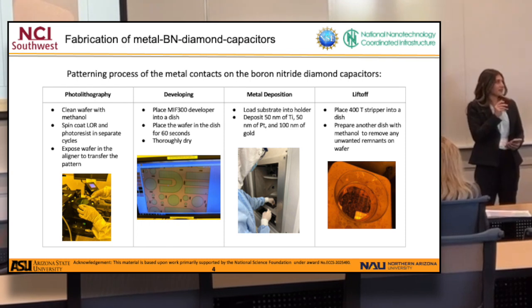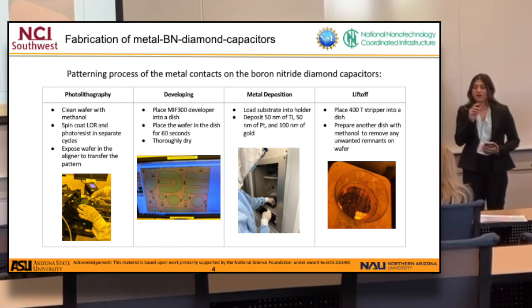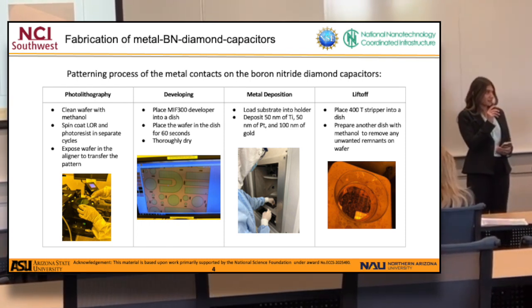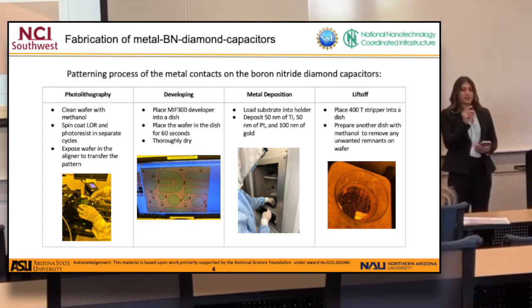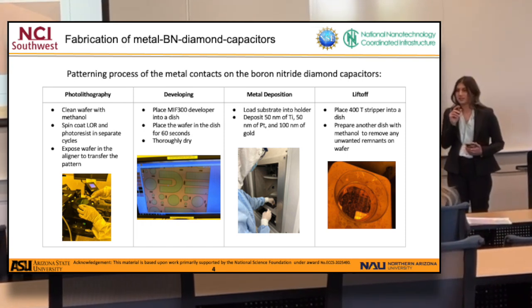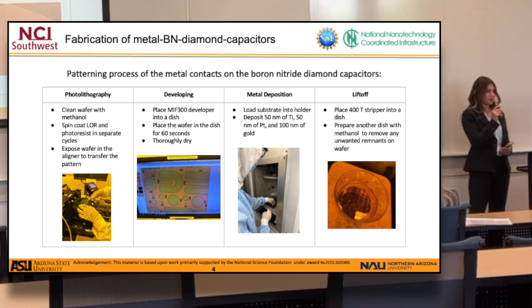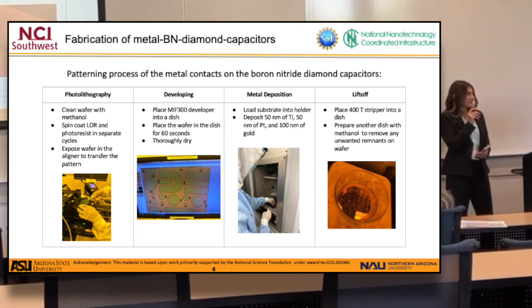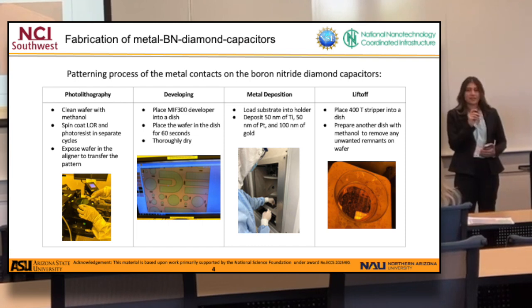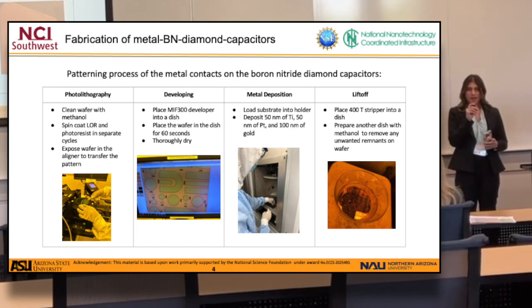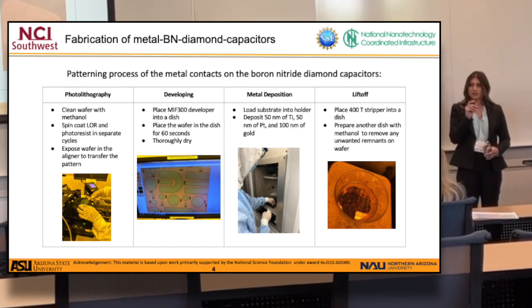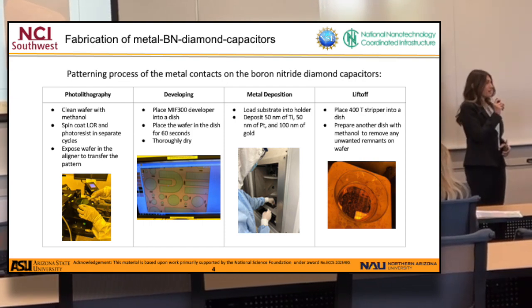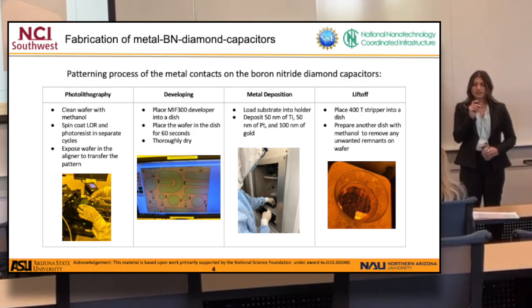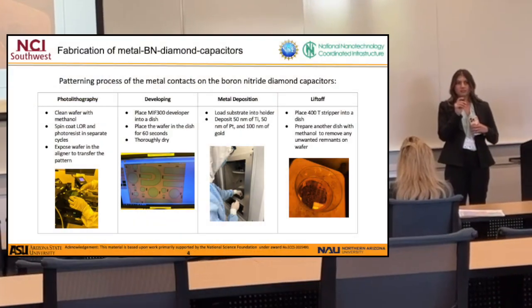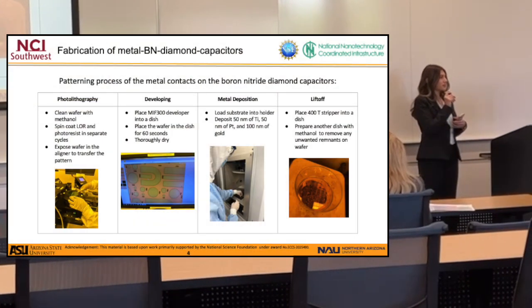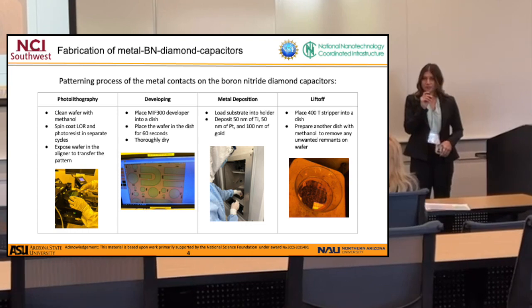So as far as fabrication of the contact metal, we did this patterning process so that we could characterize the sample's electric characteristics. So as far as photolithography and development, this was just us printing the pattern onto our substrate, and then metal deposition and liftoff were required so that we could put the titanium, gold, and platinum onto the pattern that we just made.